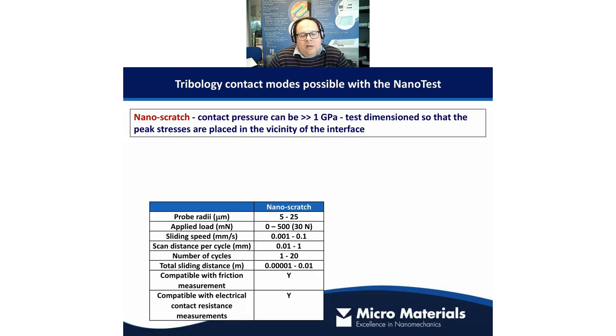The scratch testing, we tend to use, as I said, fairly small probes, so 5 to 25 micron probes. So 25 tends to be more something we'd use in micro scratch testing. The instrument load ranges are very wide. So we have on our low load head up to 500 millinewtons, and then we have a high load head that takes us to 30 newtons. And so the combination of the correct load range and probe size is a key thing to get right when designing a scratch test. Sliding speeds tend to be low, and track lengths for the scratch also tend to be small. So a millimeter would be regarded as quite a long scratch.